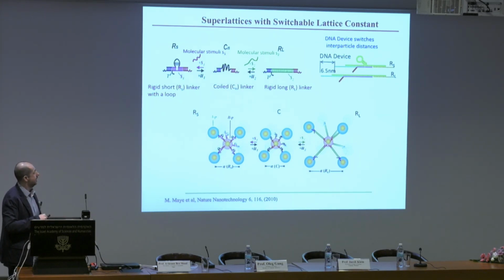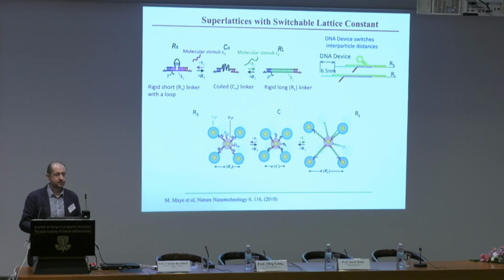For example, the particles are connected by this bridge, which is single-stranded DNA, designed in a way that with one DNA strand, it can be in this configuration. There is a loop which is stabilized, and we can remove this through a replacement reaction, go back, and be in this configuration. The difference between these configurations is approximately 6.5 nanometers, which is approximately 25% of the lattice distance. So essentially, we can start from the crystal, and by adding different types of DNA strands, we can switch the lattice constant in this type of organization. Changing the distances is interesting, but it's not so exciting.